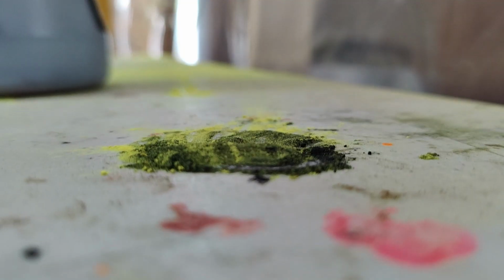Gravity is still a force and also attracts those particles. At this point, the powder coat is just loosely applied to your part. And it's really easy to knock it off by brushing your part into something or by even jiggling it too hard when you're moving it, which is a downside. But the upside of this is that if you decide that you don't like the coating on your part, if you have too much powder in some places or if it's uneven or whatever, you can take an air gun and blow off the powder and just start over again. You don't need to go through the whole finishing process again of degreasing and sandblasting and all of that and removing the old coating. All you have to do is use compressed air and you can start again. That makes rework way quicker and easier than with Cerakote.